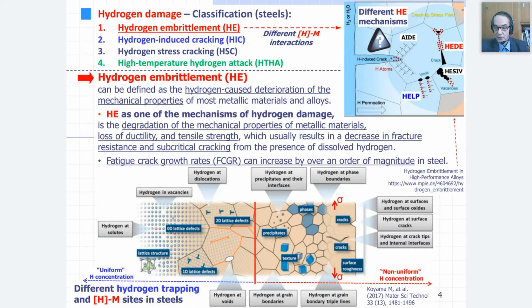What is the definition of hydrogen embrittlement, to make the clear distinction between hydrogen embrittlement and other hydrogen damage mechanisms? Hydrogen embrittlement can be defined as hydrogen-caused deterioration of the mechanical properties of most metallic materials. So, hydrogen embrittlement is one of the mechanisms of hydrogen damage, the degradation of mechanical properties of materials, particularly a loss of ductility and sometimes a loss of tensile strength, but not always, which results in a decrease in fracture resistance and fracture toughness of the material, which finally produces subcritical cracking from the presence of dissolved hydrogen and various hydrogen embrittlement mechanisms. It's important to know that the fatigue crack growth rate can also increase by over an order of magnitude in steel, and we will talk about this later.